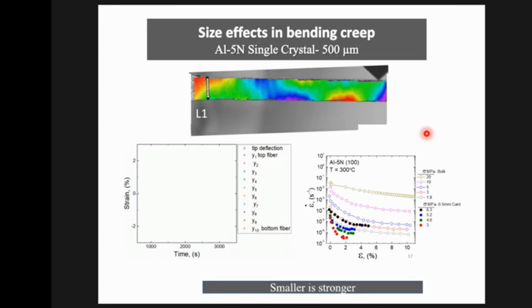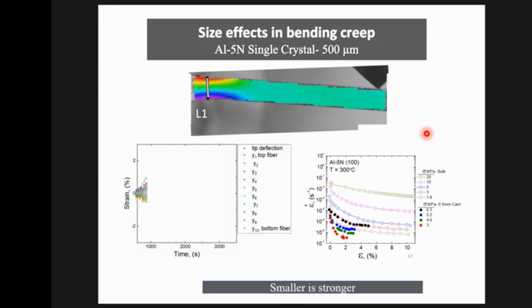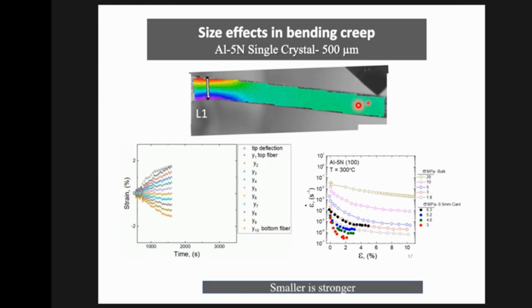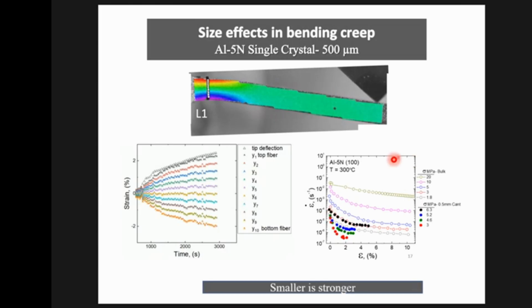So you'll see exactly the same bunch of curves. So this is that beam bending. And there's a bunch of creep curves that you see here on the left developing. Now, when you plot the data, what you find is that the bulk data, bulk meaning in this case anything above about 3 millimeters or larger, essentially gives you a scale independent behavior. But when you test these smaller beams, you find that there's a strengthening by a factor of anywhere from 10 to 100. So in bending, small beams are stronger.